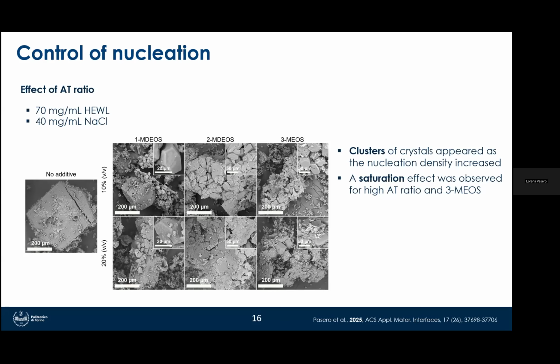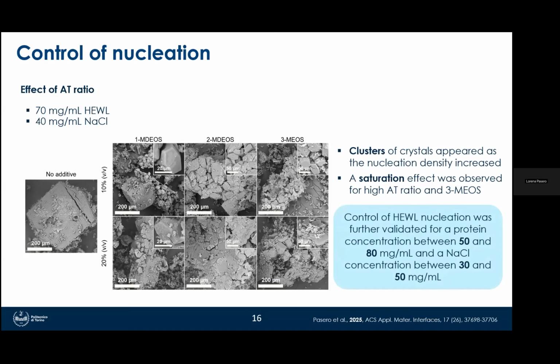But overall, we then repeated this study for different concentrations of protein and salts, and we could assess that the control of lysozyme nucleation was obtained, and it was validated for a broader range of protein and salt concentrations. And so here we could see that effectively the control of nucleation could be achieved by modifying the gel structure.